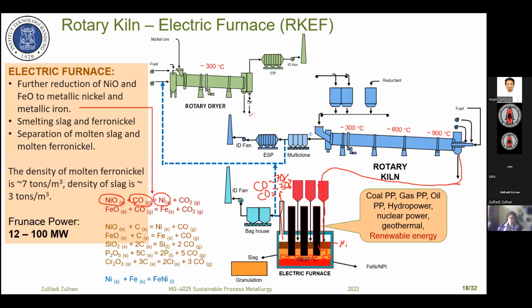And just a small amount of CO gas is utilized to reduce nickel oxide and also to reduce the iron oxide, because it's a short distance, and the contact time of CO with this calcine is also very short. And then iron oxide also can be reduced with the CO gas into iron, and the product is CO2.